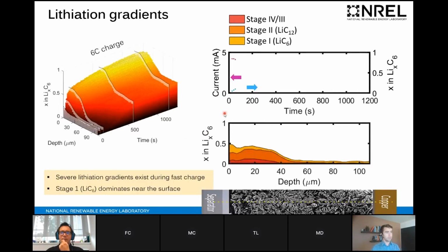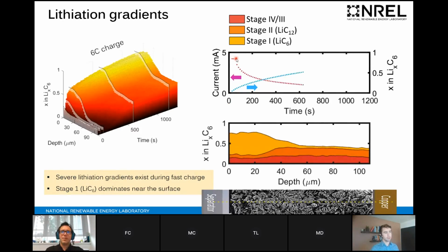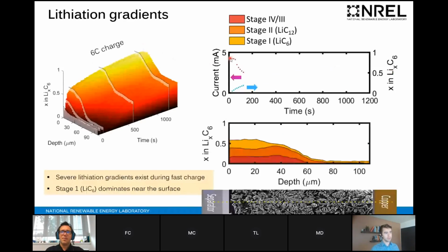And we can play this in real time. So this is the current. We achieved 6C actually for about 40 seconds or so, and then it went to constant voltage. These are thick electrodes, so the 6C constant current we didn't expect to last beyond about 40 seconds because of the overpotential needed to drive that current. And you can see the evolution generally of the x in LixC6, which is in blue here. The state of lithiation is growing. The current goes constant current and constant voltage.